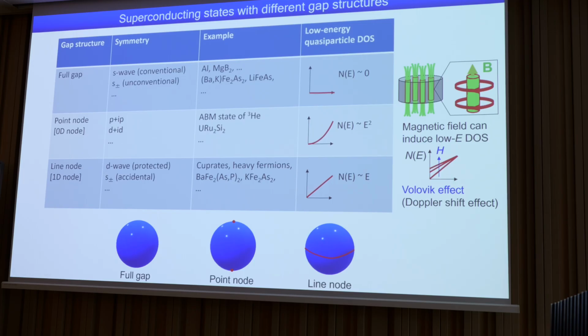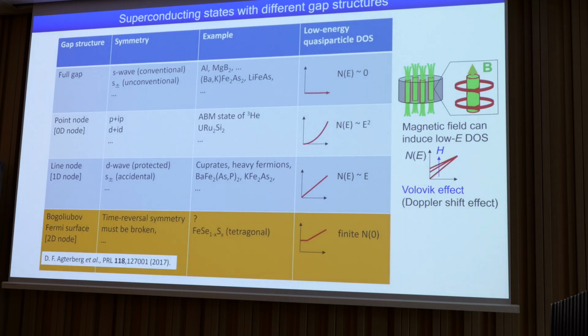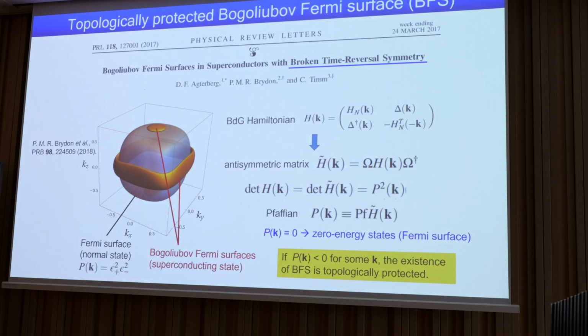So far so good. However, very recently there is a theoretical suggestion started by Daniel that you may have another type of superconducting gap, which has two-dimensional nodes, called a Bogoliubov-Fermi surface. This is a very exotic superconducting state. If you have this kind of Fermi surface, you immediately expect a zero energy quasi-particle density of states. But this requires a very exotic superconducting state, which means you need time reversal symmetry breaking. This is seminal work by Daniel.